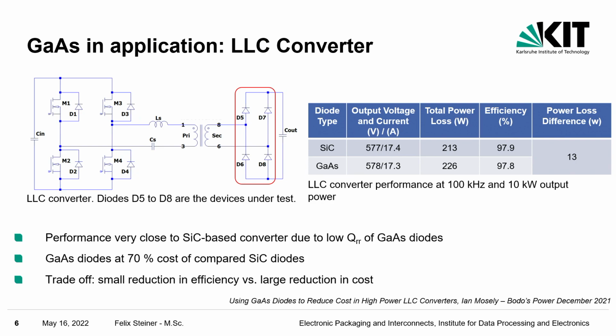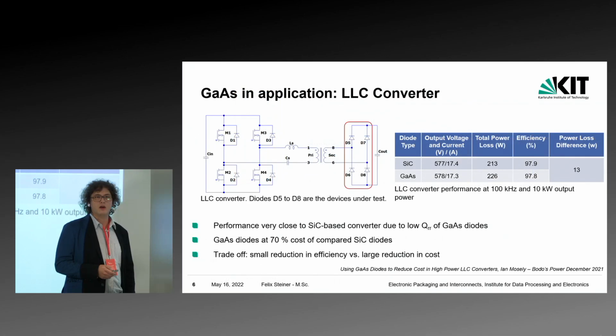With an LLC converter running at 10 kilowatts at 100 kilohertz, we see a difference in power loss of only 13 watts, where the gallium arsenide underperforms slightly. But the gallium arsenide diodes are at only 70% of the cost of the silicon carbide die. So you get a trade-off of minimal power losses but a quite large cost reduction for the dies.